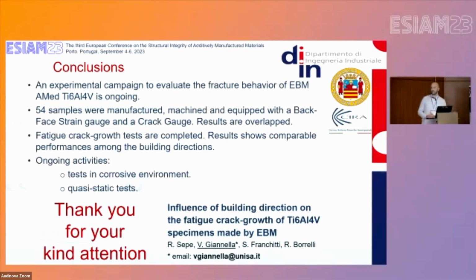It is standardized. So we just glued crack gauges at the two sides of the specimen, because it is so small, just to verify that the crack length measured was the same at both sides of the specimen. We did not observe the microstructure of the surface.